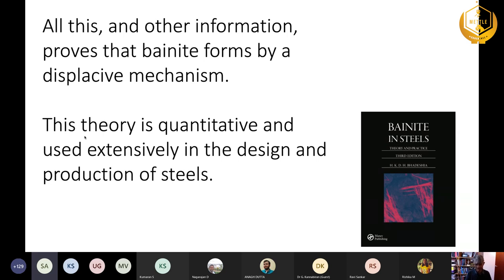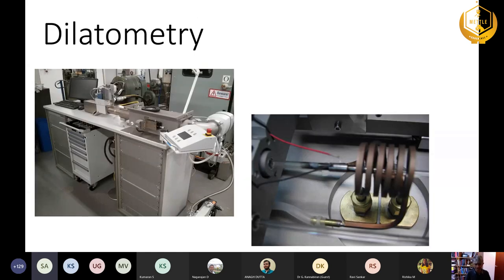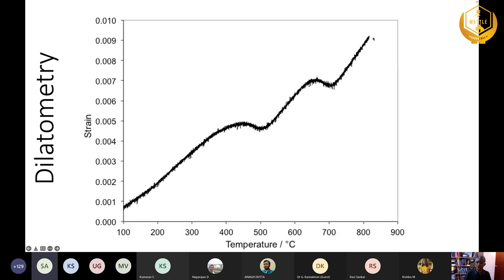Earlier I mentioned that you are probably familiar with real-time experiments on a dilatometer. This is a standard dilatometer — you put a sample in, you have a system for heating the sample, and you measure dimensional changes from which you can record a transformation actually happening. For example, this particular specimen is a nuclear pressure vessel steel cooled at a particular rate, and you can see a high-temperature transformation followed by a low-temperature transformation.